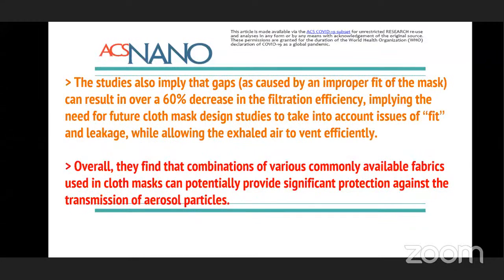Their further observation is that the study also implies that the gap, meaning the improper fit of the mask, can result in over 60% decrease in filtration efficiency. So this is a very important observation, and it is very important that you fit your mask properly to the face for maximum protection. If your mask is not properly fitted, then there will be a 60% decrease in the efficiency of the mask. So you should properly fit your mask to the face so that it can give a better result.